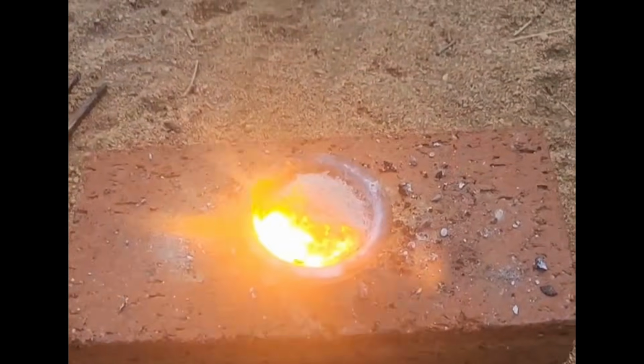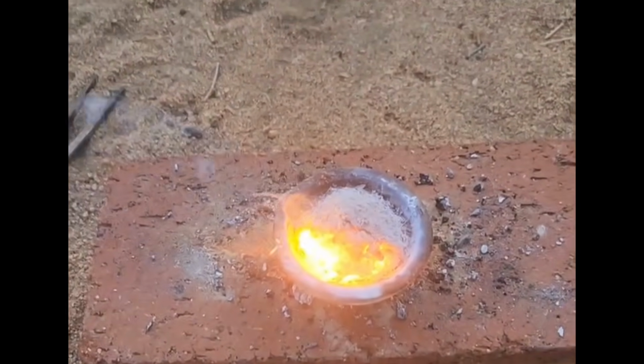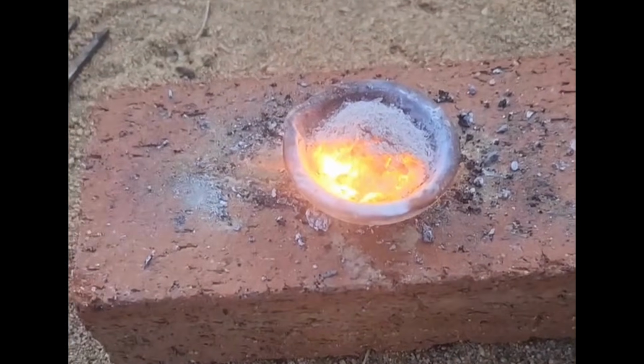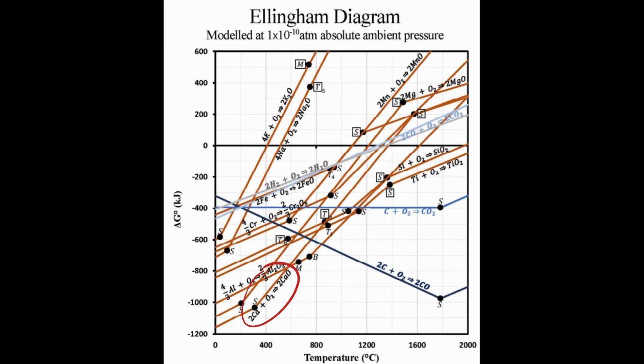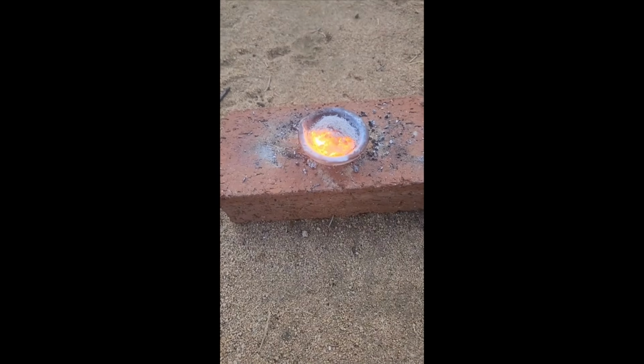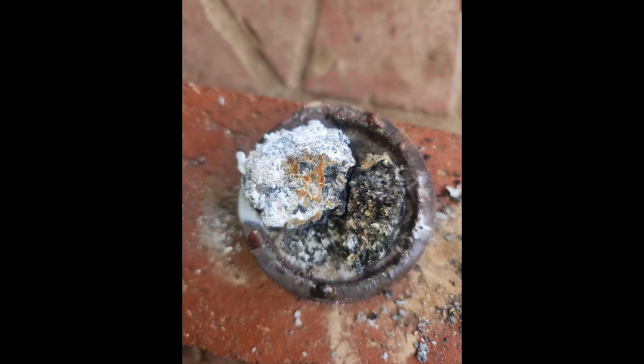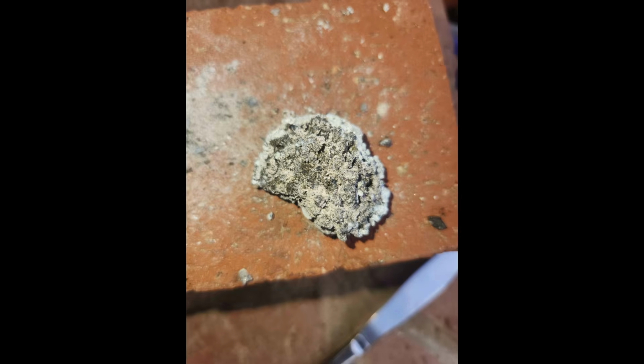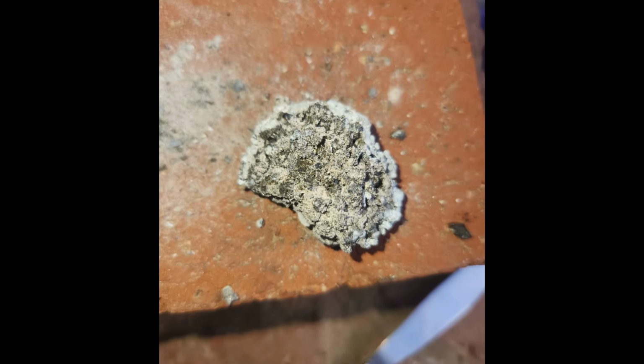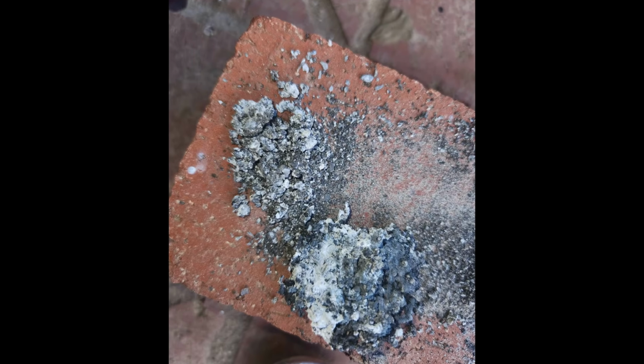You know thermite reactions? Well, those happen because aluminum can reduce most things if you get it hot enough. And as you can see on our diagram, calcium is below aluminum, so it's like an even more extreme thermite reaction, a calciothermic reaction. So we reduce regolith with calcium metal and do this pyrolysis process at much lower temperatures. And then the only oxide we would have to break would be that of the calcium oxide. So this is really promising.